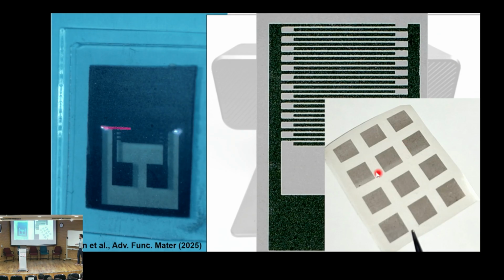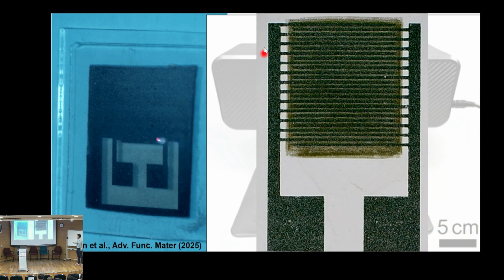Now we can go to the scotch tape. We can do squares with tungsten diselenide, molybdenum disulfide, whatever semiconductor that we want, stamp it using this thermal release transfer, and then we have an instant device. No lithography, hassle-free fabrication of devices. So this allows you to fabricate devices without any microfabrication, any metallization, all van der Waals.